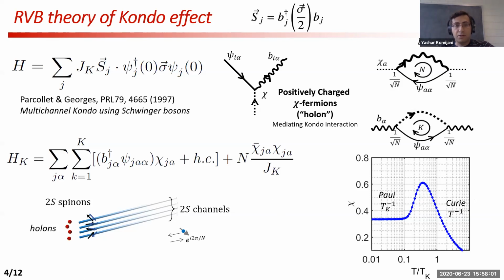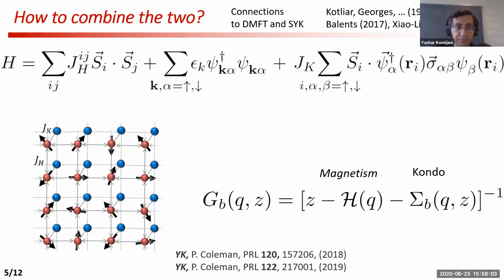Okay. So now, how can we combine these 2 together? Remember that we have a 2 layers lattice, so a lattice of moments in red and a lattice of conduction electrons in blue. They are coupled together. It turns out that all we need to do is to modify the propagator of the spinons to have a kinetic term coming from the magnetism and a self energy which comes from the Kondo effect. And there's some connections to the SYK model and also to the DMFT. But computationally, this is still difficult to do.